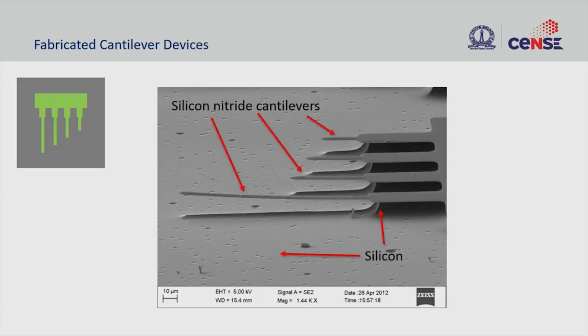Just to give you an idea, this is a scanning electron microscope image, an SEM image, of the cantilever that we just saw. So these are all the cantilevers. This is nothing but the silicon nitride cantilevers, right? As I mentioned, the long cantilever is not flat, and that is the reason why you are unable to focus across the length, while the shorter ones are really flat. So we were able to focus it, and we can see here nicely the isotropic nature, right? So you can clearly see, because of the isotropic nature of the silicon etch, you see this nice curved edge, right? And you can see something like a shadow here.